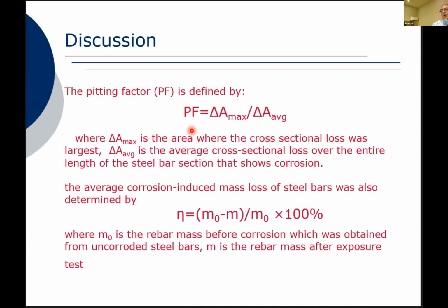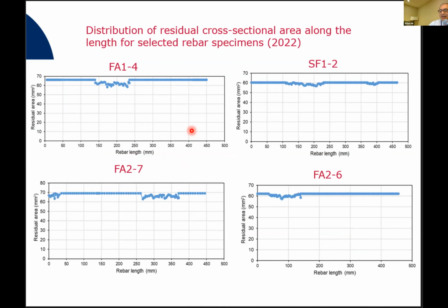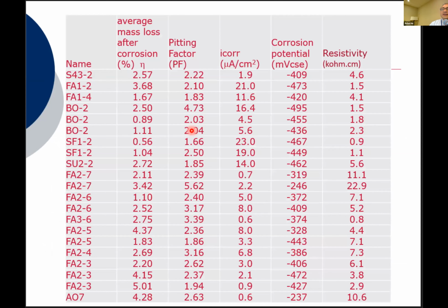And we also calculated the average corrosion-induced mass loss. Since we measured where the corrosion took place, we know the loss in the diameter. We can estimate the updated mass of the corroding rebar with respect to the initial mass of the rebar, and that we are calling eta. So let me show you, well, I'm going to skip that because of time constraints. Here is the table showing you all the rebars that we opened as part of this project, and the corresponding eta values, pitting factor values, and the electrochemical measurements right before the samples were terminated.